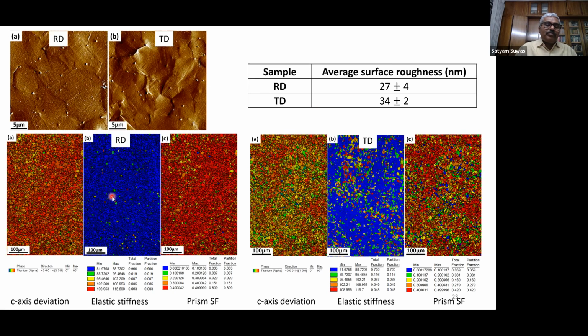Well, for these two samples, we also measured C-axis deviation, elastic stiffness, and prism Schmid factors, which were considered accountable for the dwell fatigue response. And we could see here that there is a substantial difference. The roughness, particularly in this case, is about 27 and 34, so about a 20% or 25% difference between the two. And there is a difference in the prism Schmid factor here. Again, a similar investigation was done in the previous case also, but in this case, we completed the whole investigation on one sample for which we measured these microstructures, and we could see that there is a difference in the trend observed between RD and TD.